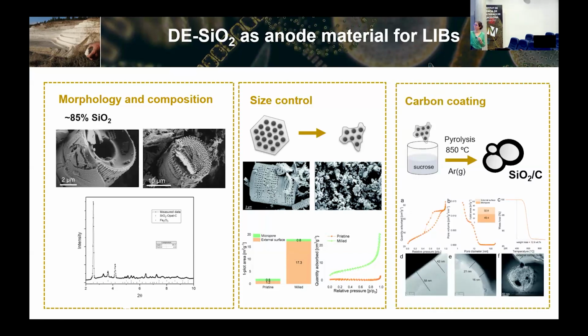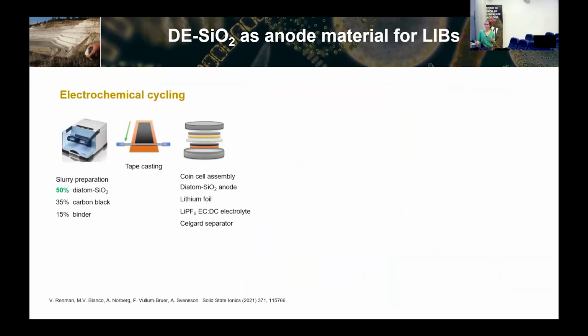We also tried some coating treatments to try to improve the electronic conductivity, because silica is an insulator, so we have to reduce the electrode resistance. We have to do some coating to the material. And we managed to make nice carbon layers using sucrose as a precursor. Then we made electrodes out of this, having 50% of this diatomaceous earth, plus carbon black and a binder, and we did the tape casting and used standard materials, standard electrolyte, and so on.